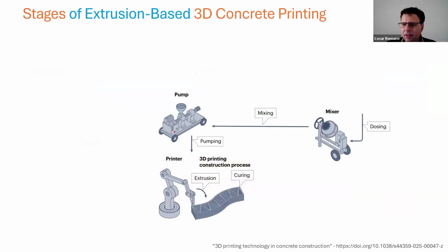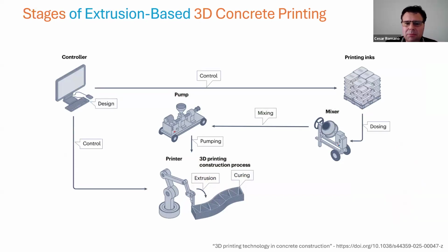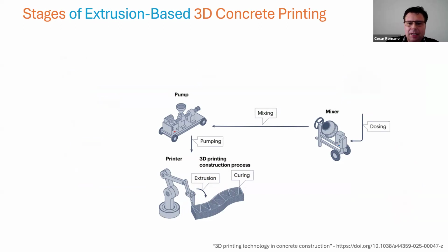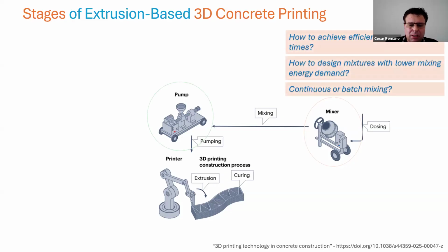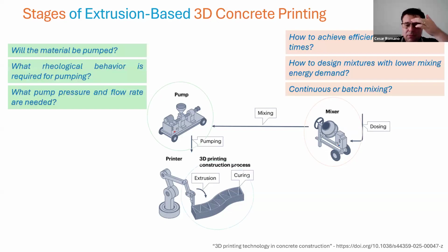For example, we have this system for 3D printing, 1K 3D printing, for example. During the mixing, the material must allow efficient dispersion of particles and admixtures, while minimizing the energy demand. During the pumping, it must exhibit stable flow under confined condition, with controlled viscosity and shear thinning behavior to limit pressure losses. During the extrusion, the material experiences very high shear rates and must flow without segregation and blockage, for example.